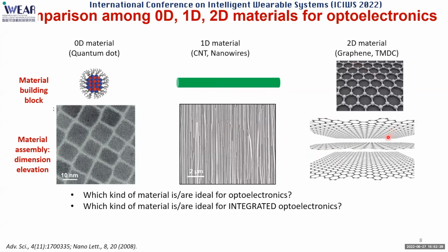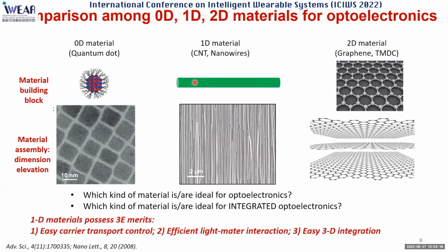If you think about 2D materials, a single layer of graphene or 2D material is very, very thin and has a very small optical absorption capability. Of course, in the other two dimensions, you can have a large area or large size, but again, when we talk about something with a dimension comparable to the photon wavelengths, it seems not an ideal material to me. Well, if you look at the nanowire, at least in the radial direction, we have two dimensions with a geometry or size comparable to the photon wavelengths, and then we can think of generating some resonant modes.